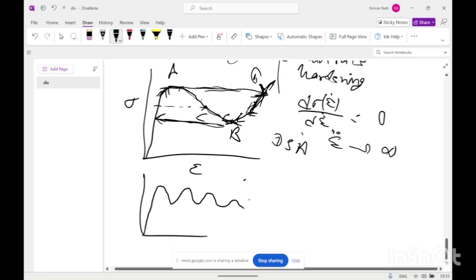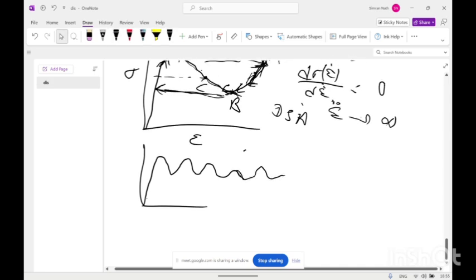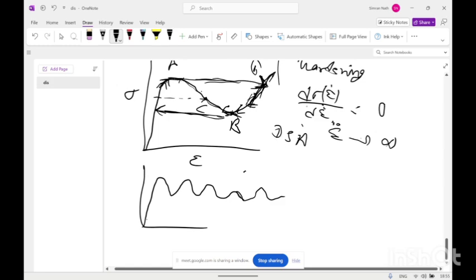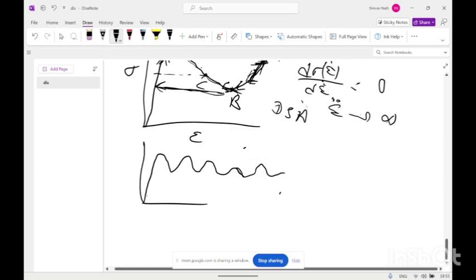So this will continue because of the inhomogeneous deformation and increasing and decreasing the strain rate because of the pinning of the dislocation with solute atoms. So this resulted in the inhomogeneous deformation and serrated flow.